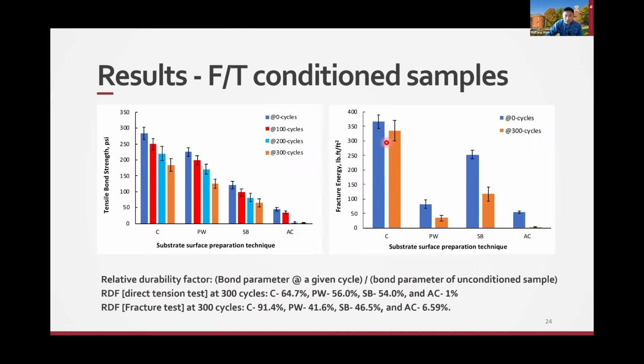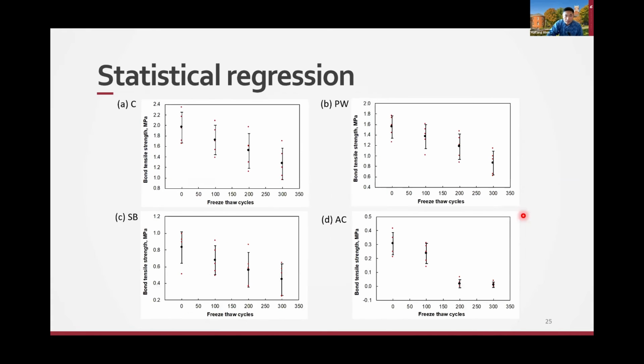Some of the bond is really weak, especially for the AC. It didn't even survive the 300 cycles sometimes, just falling apart itself. So if you look at the general trend for any of these tensile strengths, you will see that for different surface preparations, when you increase the cycle numbers, they all start decreasing to different levels.